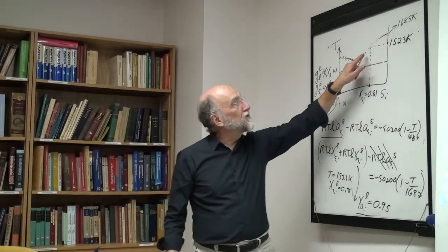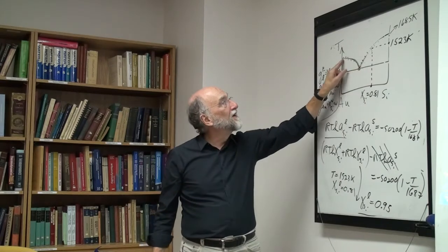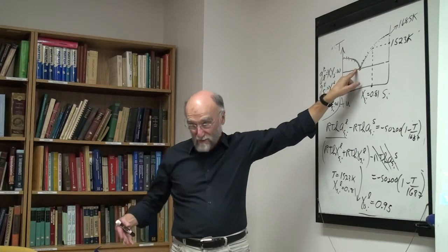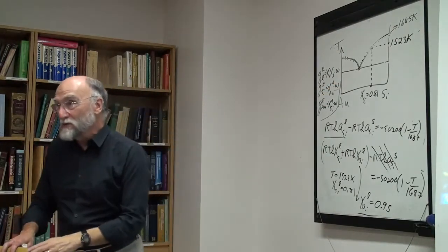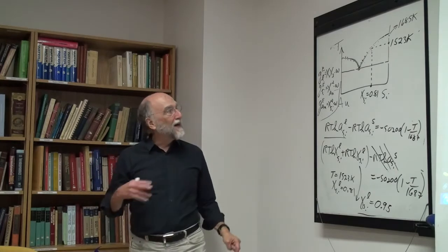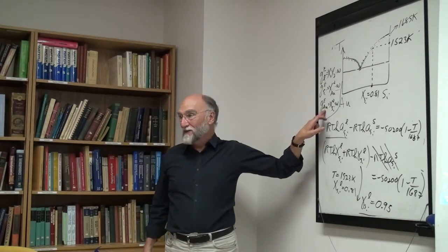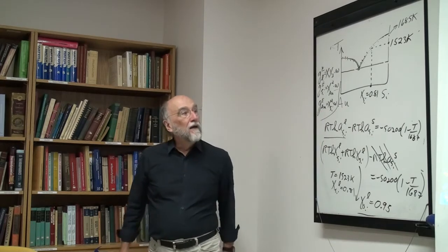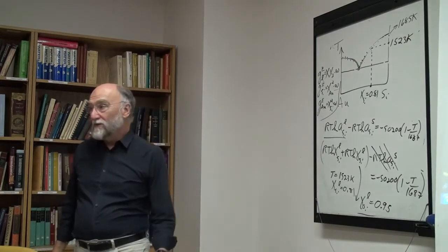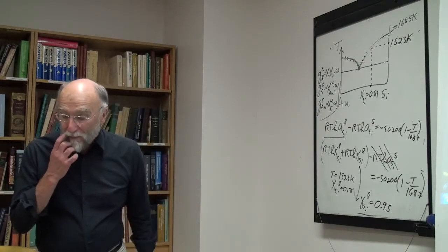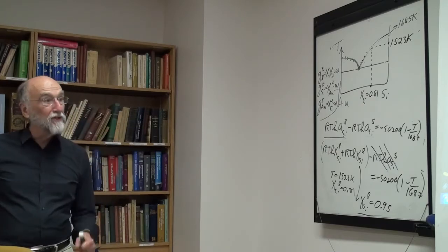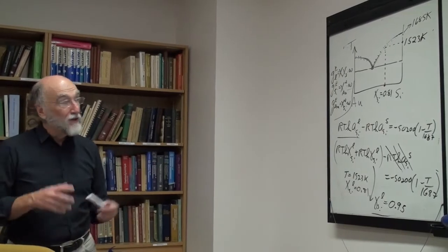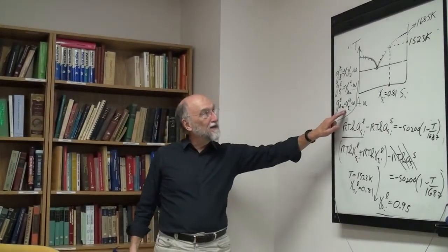And really this liquidus gives you the excess Gibbs energy of silicon. This liquidus gives you the excess Gibbs energy of gold. You don't get both. So be careful that you realize, even if the computer spews out both, you have to decide how the computer got the excess Gibbs energy of gold, because I didn't input that. You see what I'm saying? And that's why doing this kind of thing is a useful exercise. When I talk about the Gibbs-Duhem equation next week, you'll see exactly how it works and what assumptions the computer is making. This is perfectly fine, probably a reasonable way to do it, but you've got to be careful.